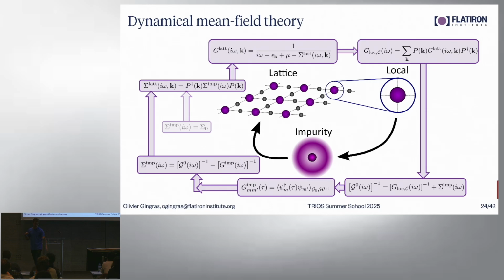If you do the one-band copper model, there's this whole discussion about the Emery versus Hubbard model, right? And it's true that you cannot capture things like the charge transfer gap, which is very important physics in lanthanum copper oxide. So the effect of the other atoms might be essential to describe some of the physics that you want to describe in the material. So it depends. There's probably an effective model that will capture correctly the physics you're trying to capture, but it's minimal in a sense. Maybe the Emery model is sufficient and the one-band model is too downfolded.